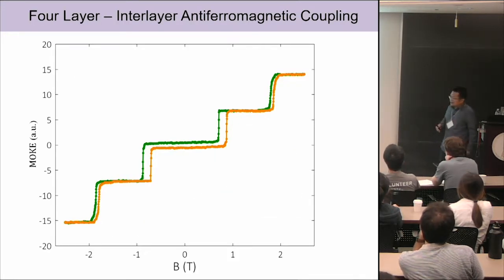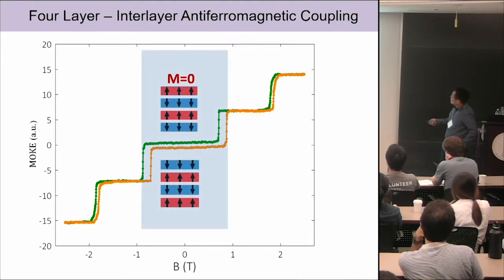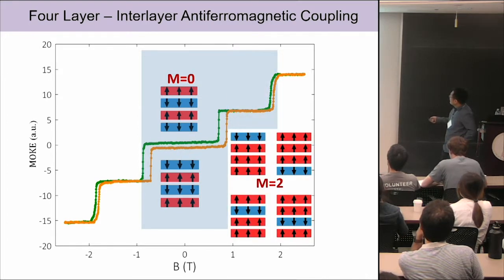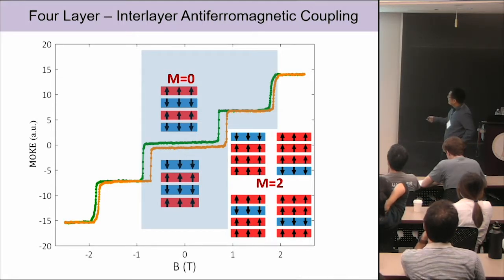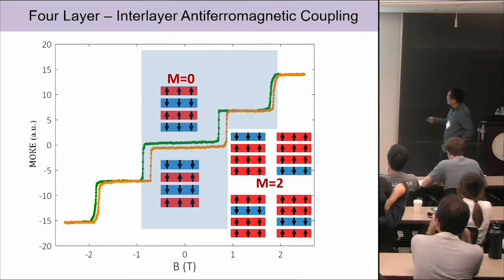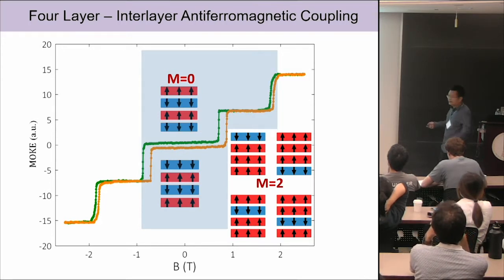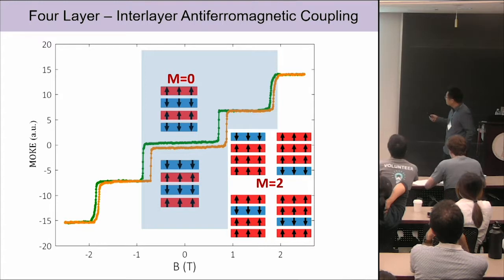We can also understand the same feature for the four layers. The ground state is up, down, up, down, with net magnetization close to 0. Once we apply a magnetic field, one layer flips. Therefore, there will be three layers pointing up and one layer pointing down. But the complexity comes from this minority layer with spin pointing down. This minority layer can be anywhere in the system, so there are four positions for it, but they correspond to the same magnetization, M equals 2. So by these co-rotation measurements, I cannot tell which one is the ground state. Later on, I'm going to show you how we can distinguish these.